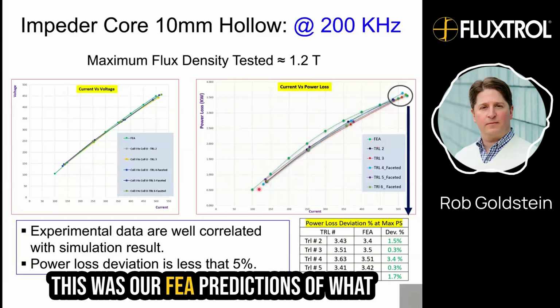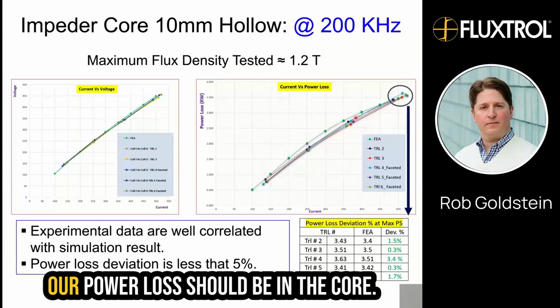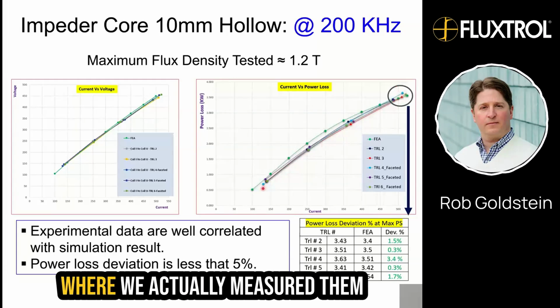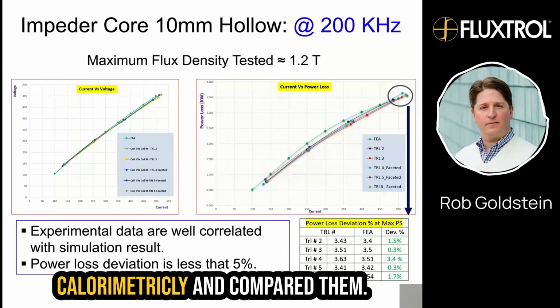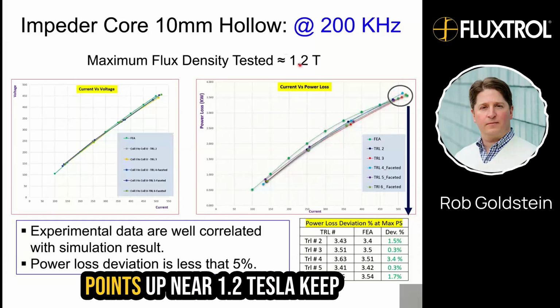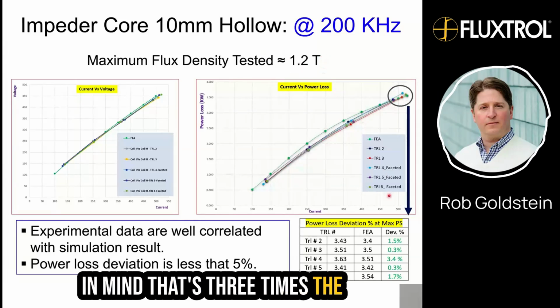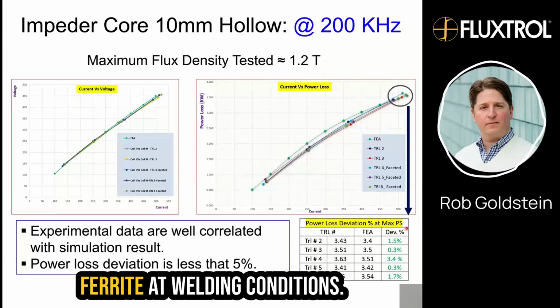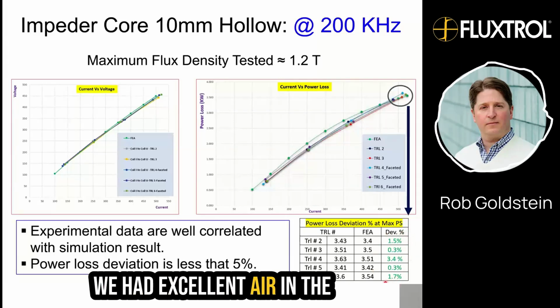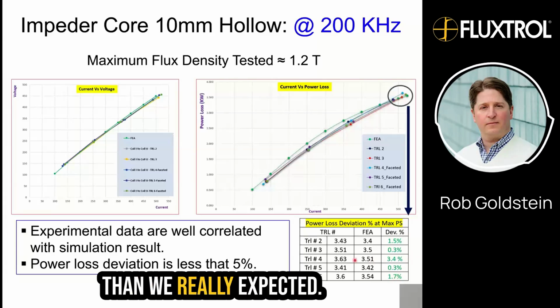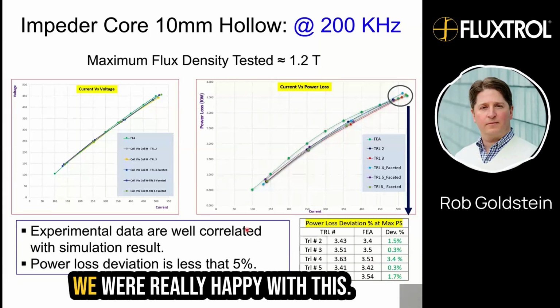This was our FEA predictions of what our power loss should be in the core, and these are our data points where we actually measured them calorimetrically and compared them. And if we look at the highest test points up near 1.2 Tesla, keep in mind that's 3 times the saturation flux density of a typical ferrite at welding conditions. We had excellent error in the system, actually better than we really expected. We were really happy with this.